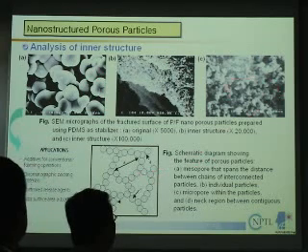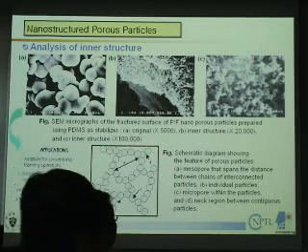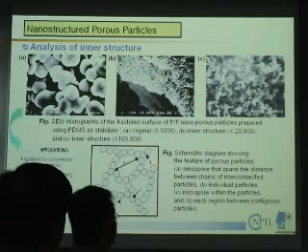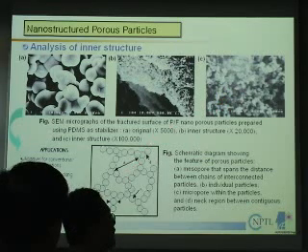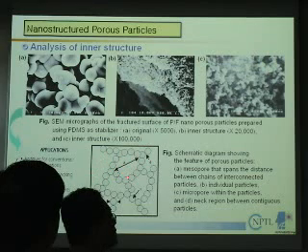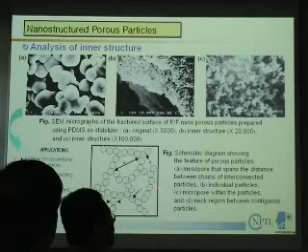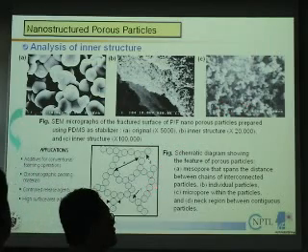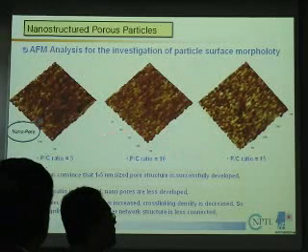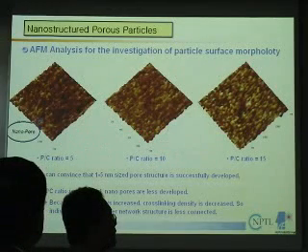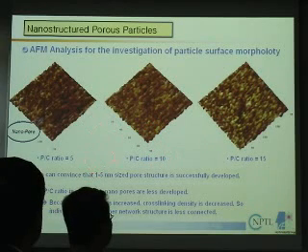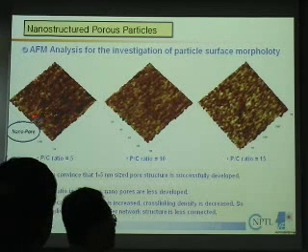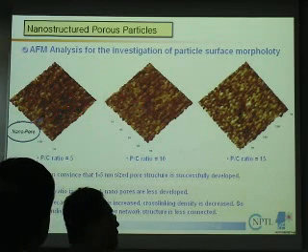And this is a schematic diagram of these pictures. Here in this area, the black part is the mesopore. And then this is the very small individual particle. Even this individual particle has very small pores. And this is the AFM result of the surface of the nanoparticles. You can see here also another evidence: this one has an open pore developed on the surface of the particles.